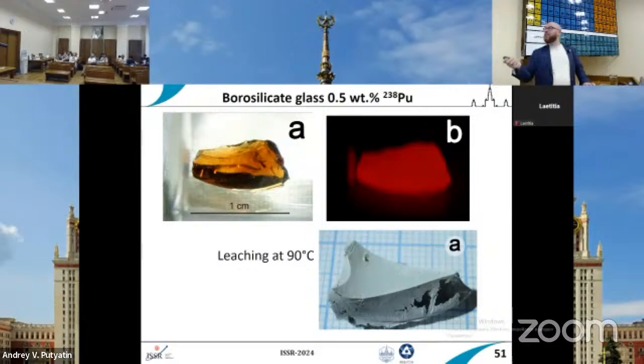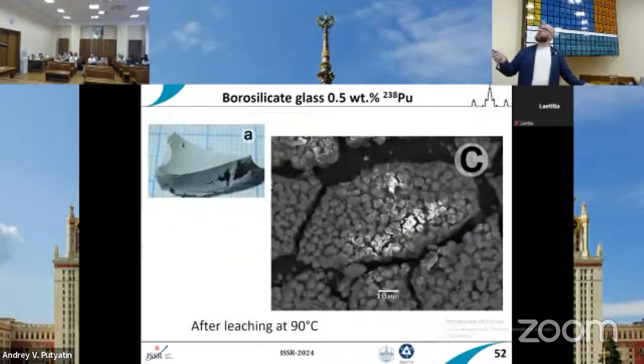But what is interesting here is the condition of this material after leaching. It was stored in water at 90 degrees Celsius for a few weeks. And you can see the very huge impact on the surface of this material. So it still was under these flakes. It was still a good glass, but the surface was changed a lot. So it's this granular-like structure, the formation of new mineral phases on the surface, and it really affects the leaching of the glasses a lot.